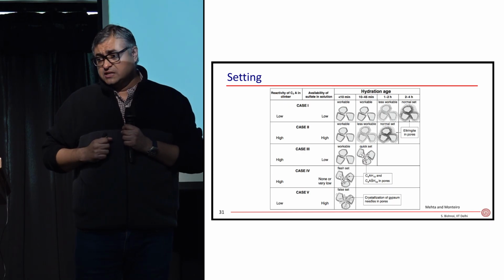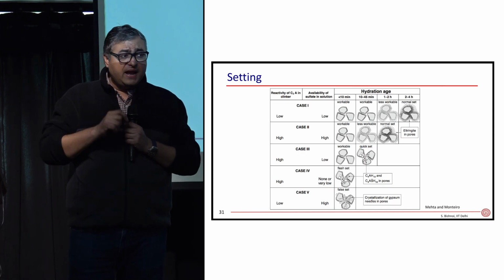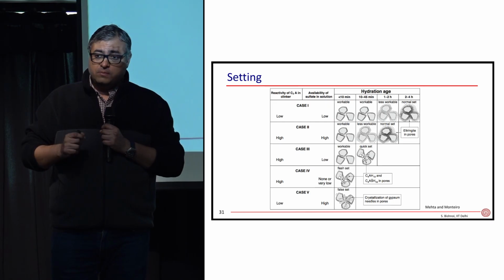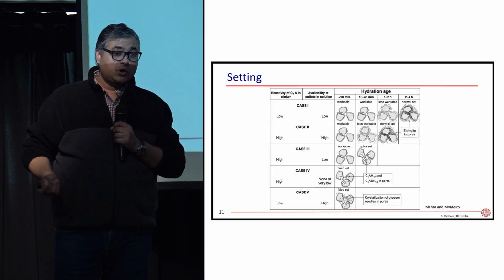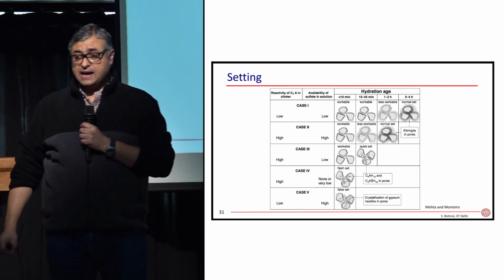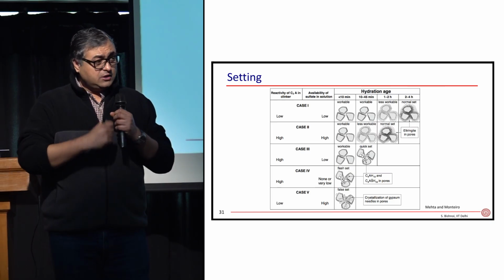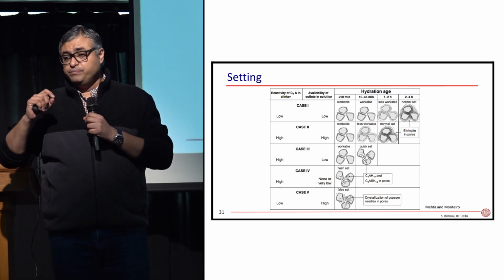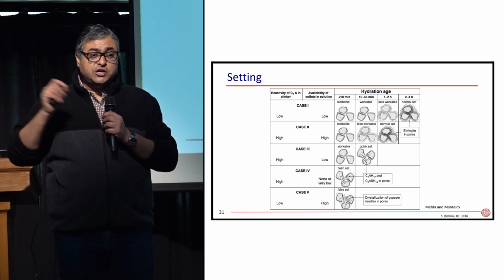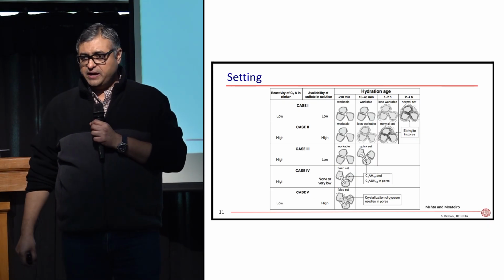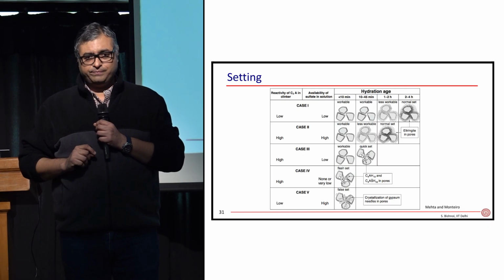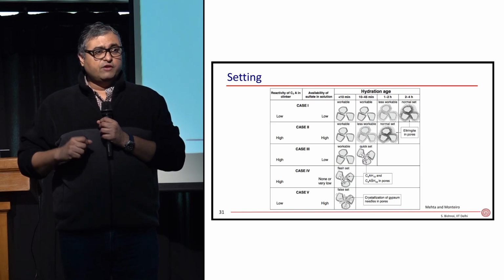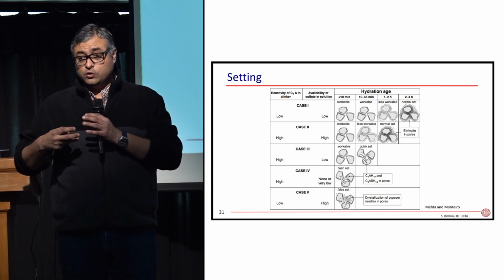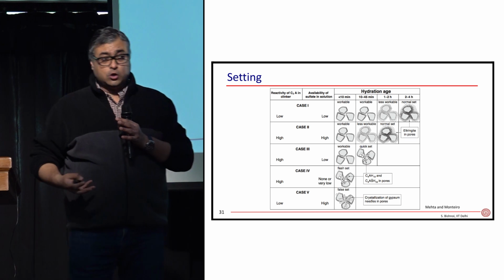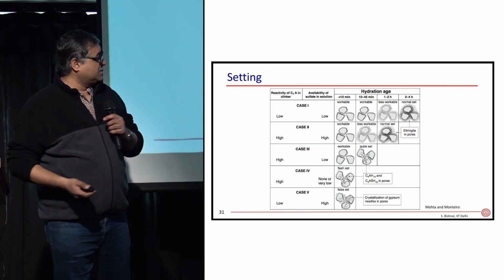You break the crystal, you are breaking bonds that were formed as a result of the energy that you had put into the cement at the time of its production. Once you break those crystals, you're losing the utility of that energy. You will permanently lose strength in the cement or concrete if you manipulate it after setting has taken place.